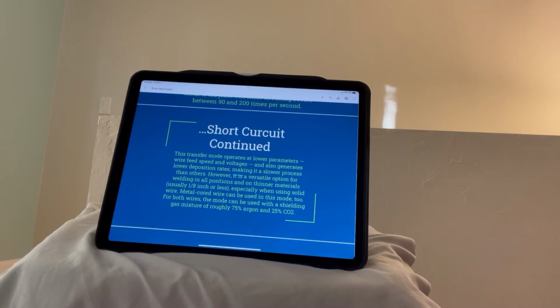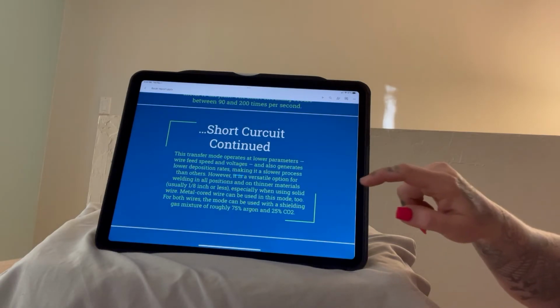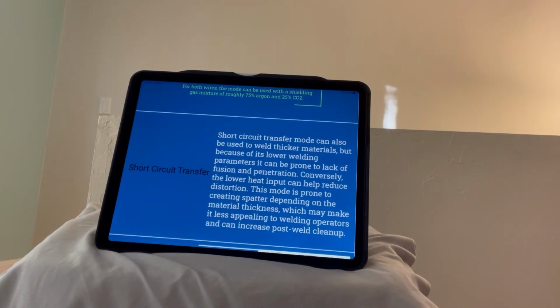Metal cored wire could be used in this mode. For both wires, the mode can be used with a shielding gas mixture of roughly 75% argon and 25% CO2. Short circuit transfer mode can also be used to weld thicker materials, but because of its lower welding parameters, it can be prone to lack of fusion and penetration.